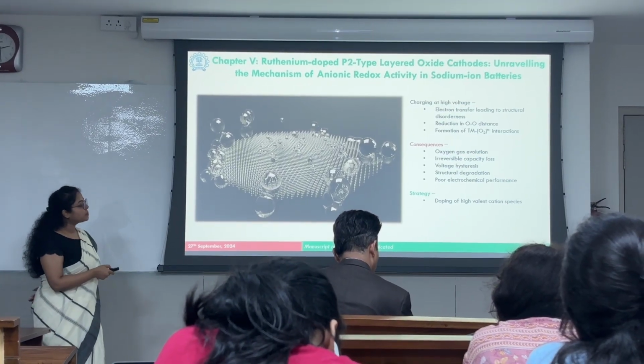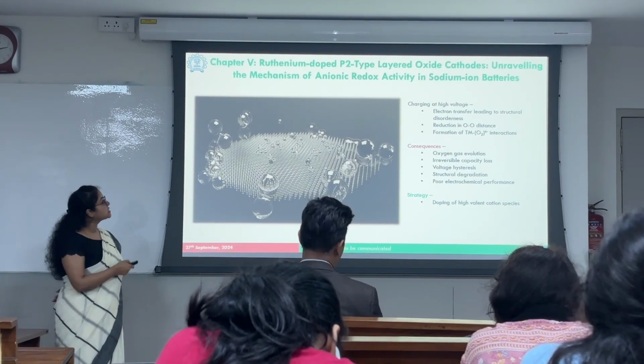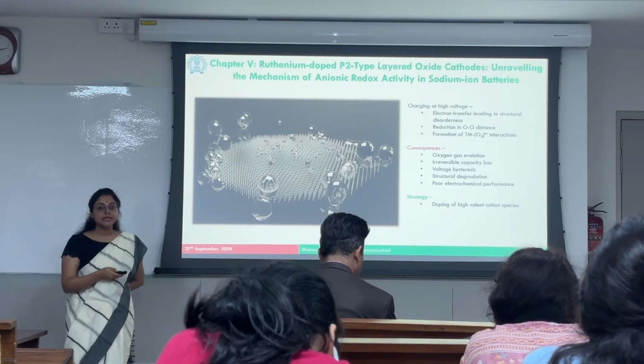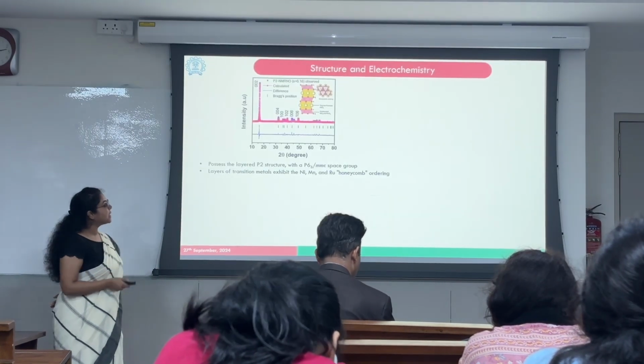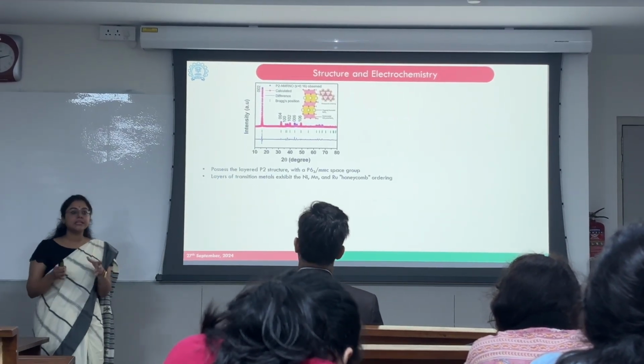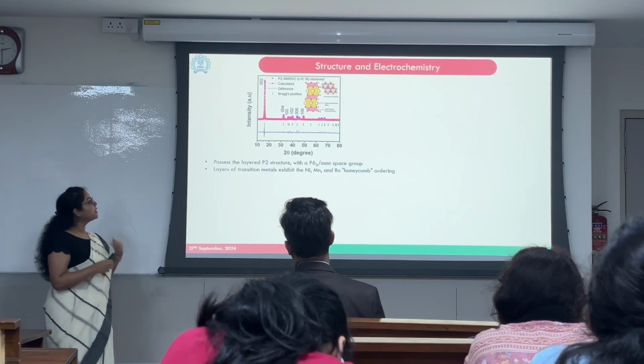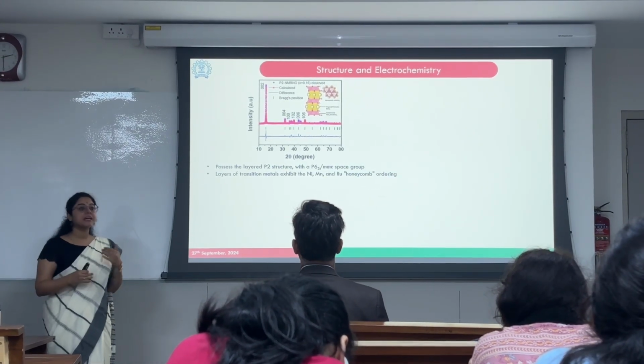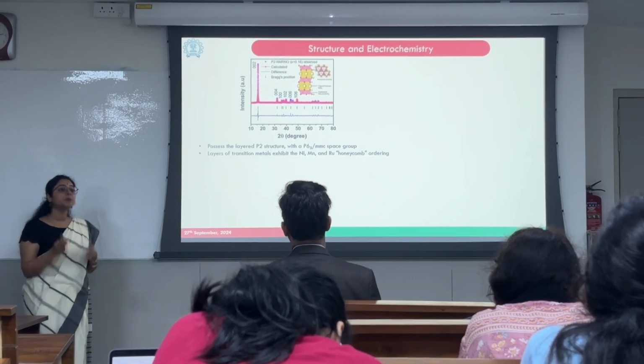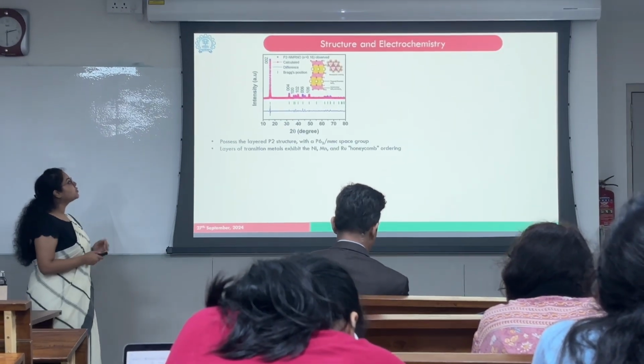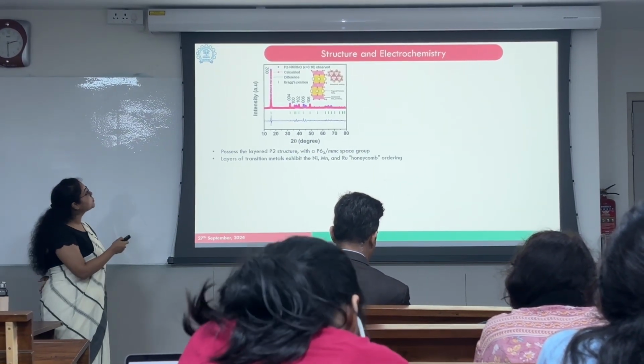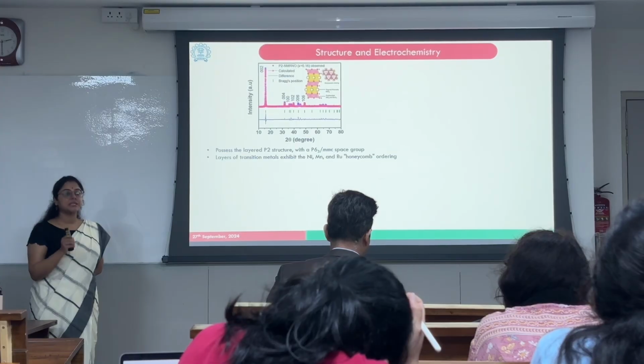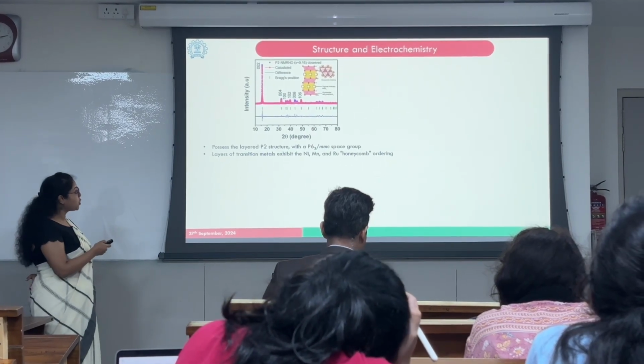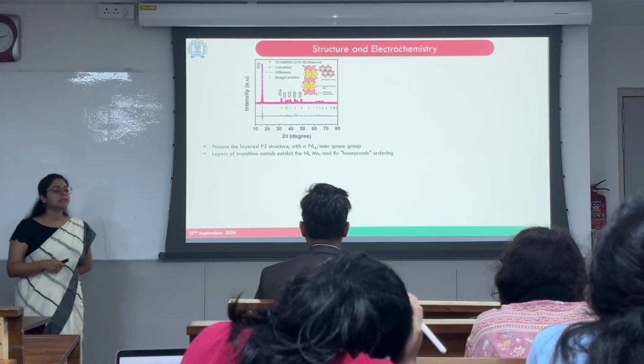So we adopted the strategy of doping a higher valent cation species, which is ruthenium. We start by optimizing the amount of ruthenium that would be useful for actually getting the proper anionic redox activity, which would be partially irreversible. We found that the 0.16 doped ruthenium gives the better result in terms of phase purity as well as the electrochemical analysis.